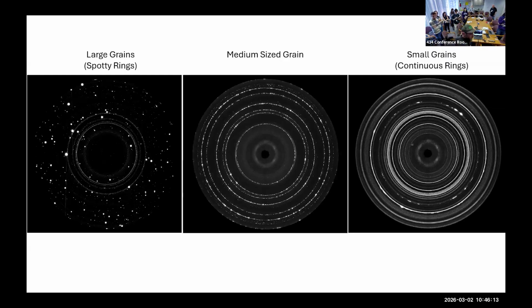One thing that happens though, when you pressurize it, and particularly when you heat it up, these single dots become smeared out. Even this sample, by the time you're deforming it at a high pressure and temperature, will actually fill out enough of this ring that you can do the analysis. But if you only had just 1 or 2 dots, you wouldn't be able to do it.